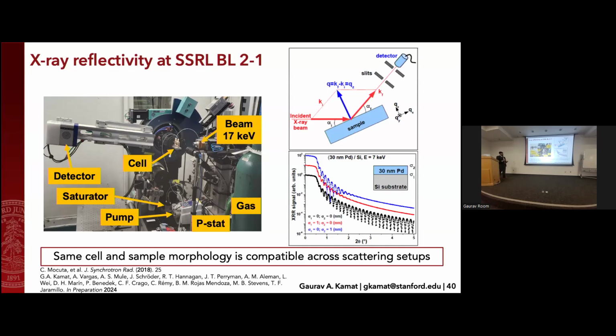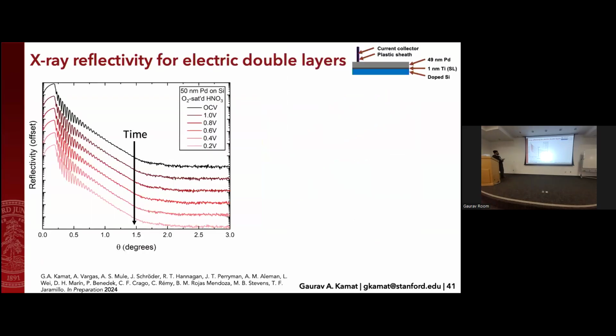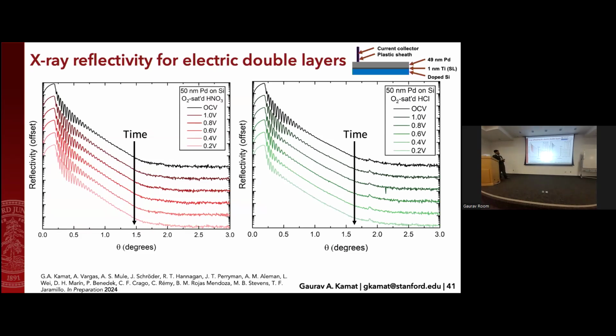So you can use this to see the roughening that's happening on your surface. And because it's the same exact cell and sample morphology that we did for the X-ray diffraction study, we can bridge a lot of the same conclusions that we see. So here's an example of some of this data for palladium in nitric acid. As we start at open circuit potential and then apply lower and lower potentials as time goes on, we don't really see any major changes in the reflectivity signal. And if we compare this to a chaotrope such as chloride or hydrochloric acid, and we specifically look at this region, you can actually see that these fringes are starting to disappear as you go lower and lower in potential, whereas that's not really happening in the case of nitric acid.